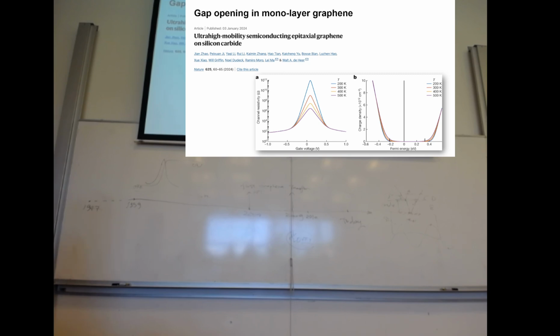And recently, in 2024, this year actually, there's a paper from Walter de Heer's group. What they published in Nature is that if you grow graphene on top of silicon carbide, they managed to find somehow a broad peak and a very insulating phase, with very conductive peaks outside of this insulating gap. So the mechanism behind that is not clear enough. There might be some interfacial couplings.